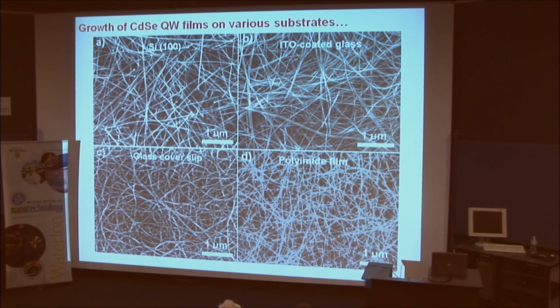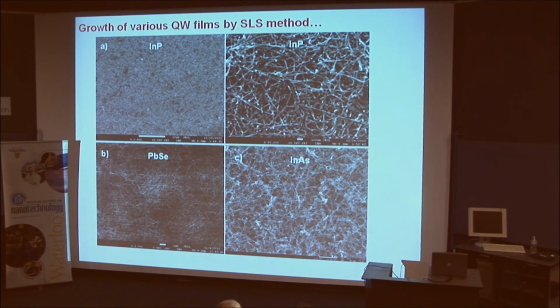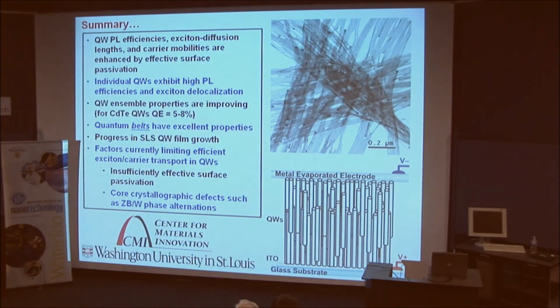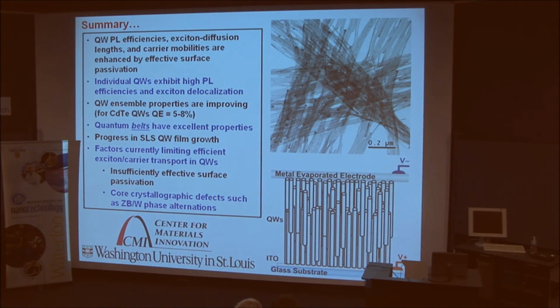We can grow on a range of different substrates. This is silicon 100, ITO-coated glass, polyimide. And we can grow a range of different materials, indium phosphide, indium arsenide, lead selenide, for example. So these are just some initial, fairly preliminary results of our efforts on quantum wire film growth. Okay, so let me summarize.